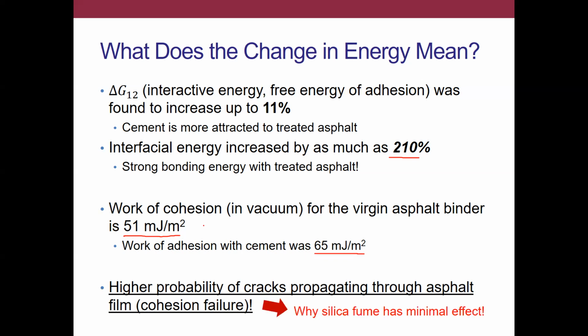And indeed, this would be exactly why silica fume has no effect, right? Because yes, silica fume is improving the properties of the ITZ. It is reducing calcium hydroxide. It's slightly reducing the porosity, but there's no effect on strength. That's, again, because even though we improve the ITZ, the cracks still propagate through the asphalt. So there's no benefit of the ITZ.